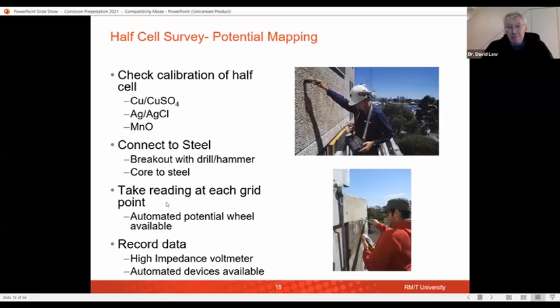And to do this, we would have a half cell. That is a standard electrode that we are going to use to measure the condition of the steel. Generally, when we're doing it on the surface, like these guys here, we would use a copper sulfate electrode because it's pretty robust, and so it can take the knocks that might come with it, and it will give you a pretty good idea of what's going on, perhaps plus or minus 5 millivolts in inaccuracy.